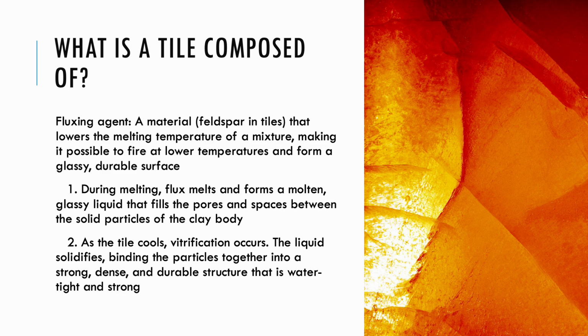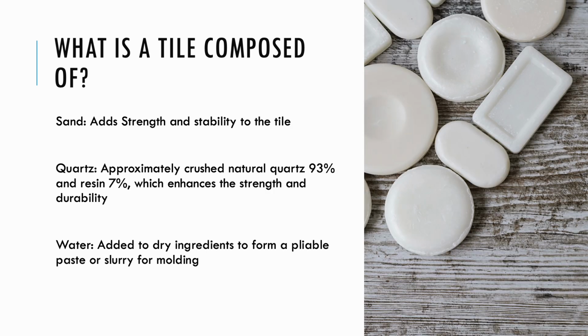During melting, flux melts and forms a molten, glassy liquid that fills the pores and spaces between the solid particles of the clay body. As the tile cools, vitrification occurs. The liquid solidifies, bonding the particles together into a strong, dense, and durable structure that is watertight and strong. Sand adds strength and stability to the tile, and quartz is 93% composed of natural quartz and 7% resin, which enhances the strength and durability as well. Water is added to all these dry ingredients to form a pliable paste or slurry for molding.